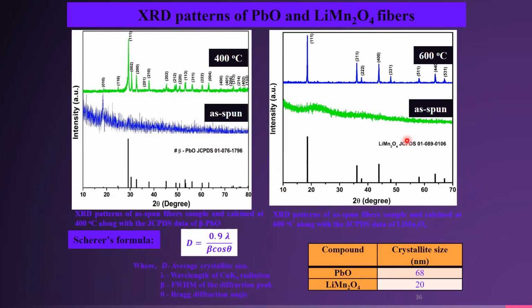Similarly, the X-ray diffraction patterns of the sample obtained at 600 degrees centigrade, compared with the JCPDS data of lithium manganese oxide, confirm the formation of pure cubic spinel phase of lithium manganese oxide nanofibers. The average crystallite size of the lead oxide nanofibers is 68 nanometers and of the lithium manganese oxide nanofibers 20 nanometers, respectively, calculated from the XRD patterns by the Scherrer formula.